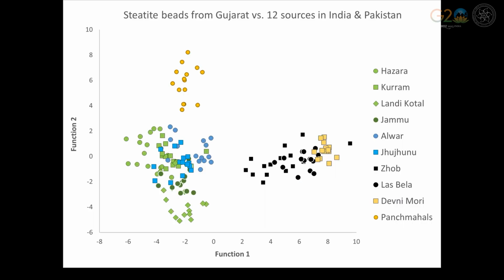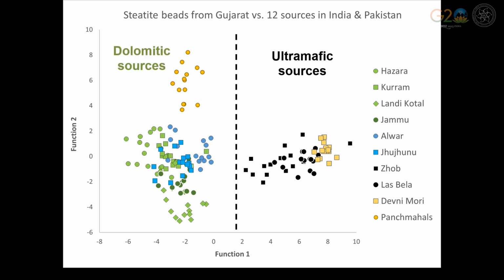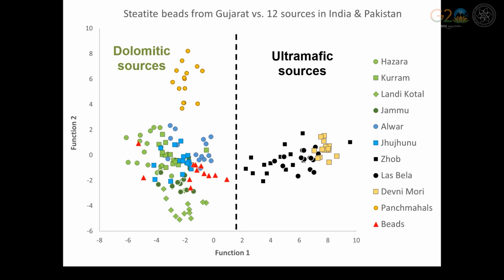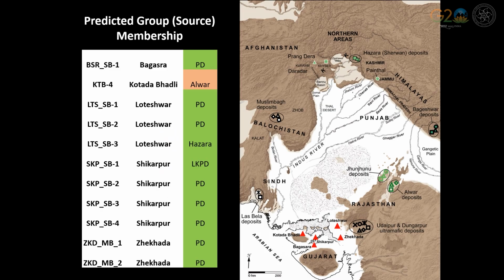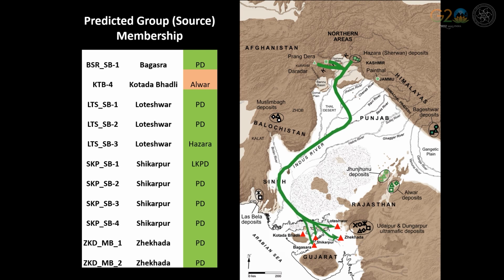Although smaller in size, our heated geologic dataset again falls into well-defined dolomitic and ultramafic sample groups. When the steatite beads from Indus sites in Gujarat are compared, we see that they all plot closely with dolomitic sources. And for most of the sites, those sources are located in the northern Indus region, which is typical. However, at one site, Kotada Bhadli in Kutch, the bead appears to have been made from raw material originating in Rajasthan.